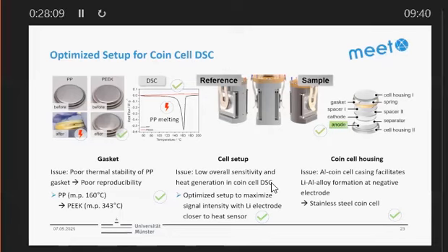And polypropylene melts at 160 degrees C, and the safety event of a lithium metal battery, the main thing, is happening after 160 degrees C. So that means you are measuring safety on an open cell, or a cell where the sealing is molten, or the sealing is half open. And this gives you very irreproducible results.